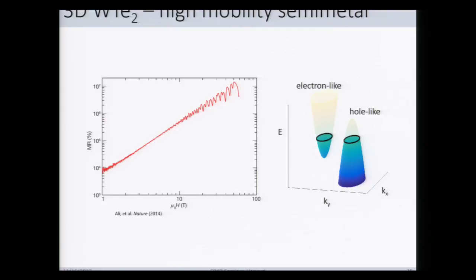This is pretty exceptional and is indicative of not only high mobility, but almost exact compensation of electrons and holes in the system. This is a cartoon. It's not an actual band structure, but just a schematic to emphasize that you need pretty close compensation to get this sort of thing. This tells you that there's no sort of intrinsic doping, and the mobility is rather high. And so that's really wonderful. We have a beautiful exfoliable crystal, and we apparently have a high-quality crystal to start with as well. Now, let's exfoliate it and see what happens.